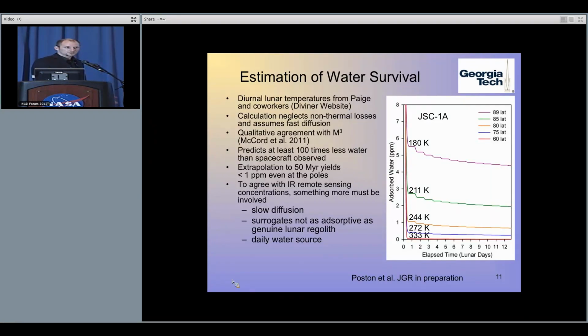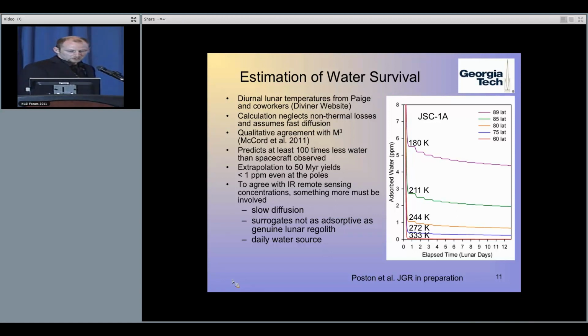If I take these concentrations from the previous graph and run them through a lunar diurnal temperature cycle at a fixed latitude, assuming a solid sphere and lots of other simplifying assumptions, I get the data over here on the right. It shows the amount of water that survives for a given number of lunations, or diurnal cycles, where the temperatures are just the maximum temperature the sample sees. Qualitatively, this agrees with the M-cube data, but we see about 100 times less than the numbers I've been able to find for the interpretation of the M-cube data.